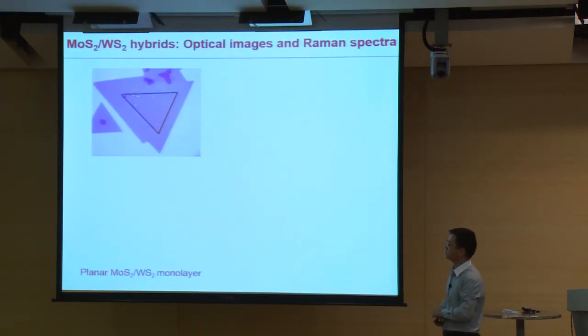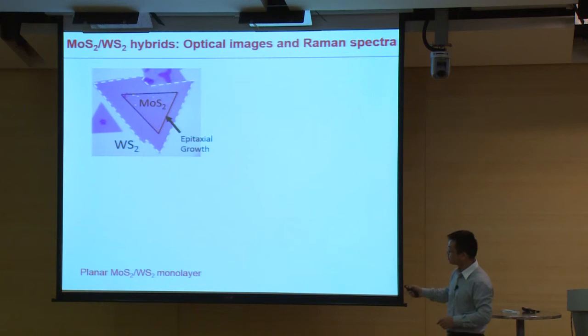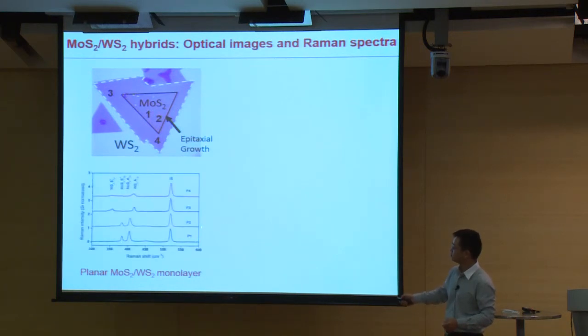Okay, in the last two slides, I will show the possibility of making some hybrid structures using the moly disulfide and tungsten disulfide. This one, for the small triangle, is moly disulfide. And we can epitaxially grow the tungsten disulfide surrounding the moly disulfide to get the planar structures of moly disulfide and tungsten disulfide. And we can collect the Raman spectrum from different sites 1, 2, 3, 4. So at positions 1 and 2, this is the signal from pure moly disulfide, and 3 and 4, the pure tungsten disulfide. So these are planar structures.